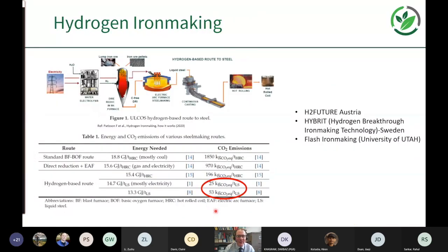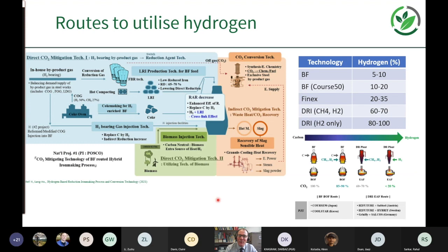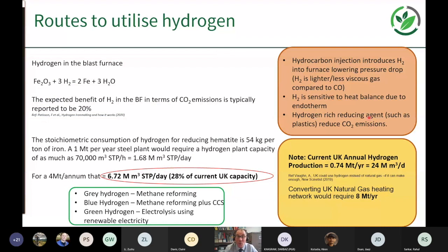So I mentioned hydrogen briefly. Of course, hydrogen has a stellar potential to reduce CO2 emissions, and there are a couple of hydrogen projects in the pipeline at the moment in Austria and in Sweden, and there's significant potential to reduce the emissions of iron production using this hydrogen-based route. There are a variety of different ways it can be incorporated into the blast furnace, but there's a limit to what you can put through the blast furnace, and then it can be incorporated at a much higher level in direct reduced iron production, or potentially if it's used as the only gas in direct reduced iron production, it could be very high incorporation and associated CO2 emissions would be much lower.